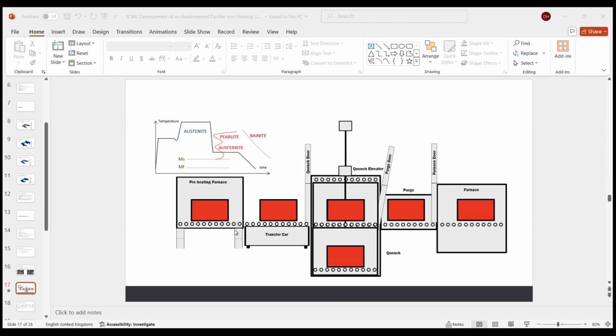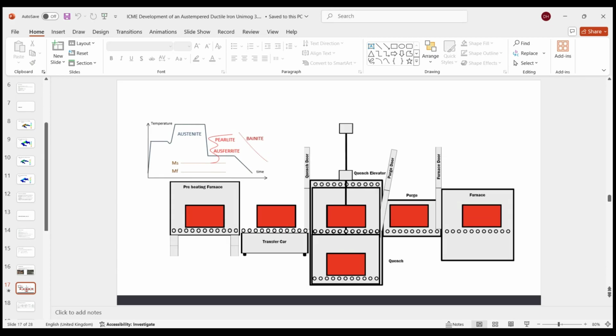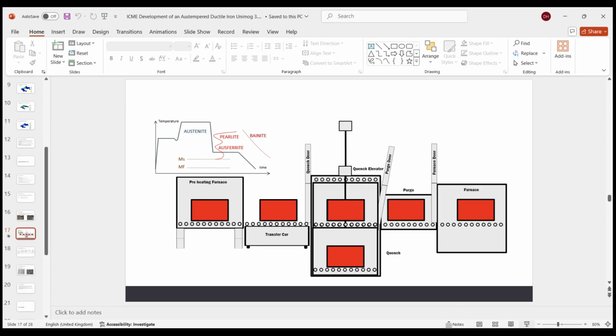So what we do is we load a basket up with the castings, in this case the lift arm. Then we take the castings and warm them up, to about 600 degrees centigrade. This is just to assist with the economics of the process, because the next stage is to take the parts into the back of the furnace, which is at the high heat. So they transfer through, and eventually they go into the back of the furnace.